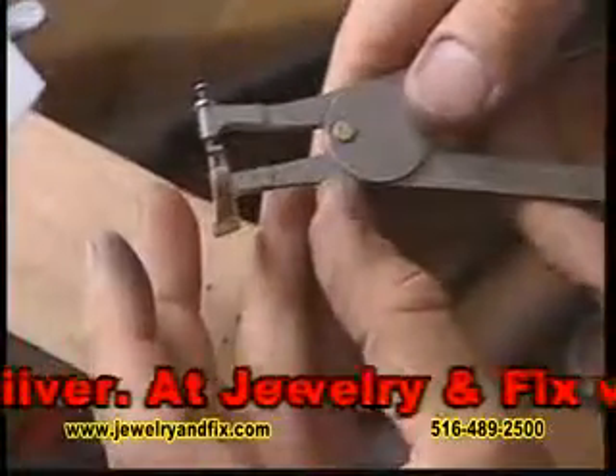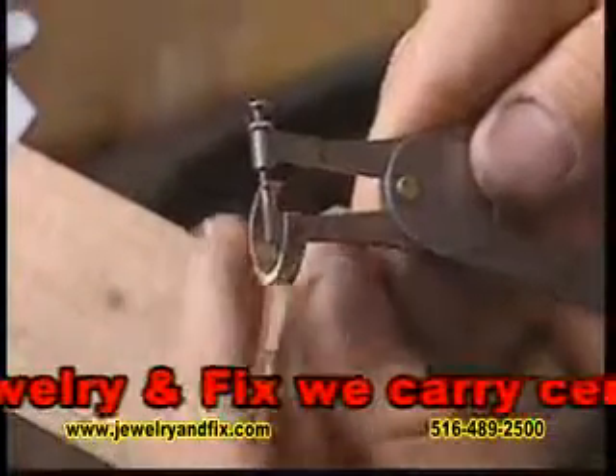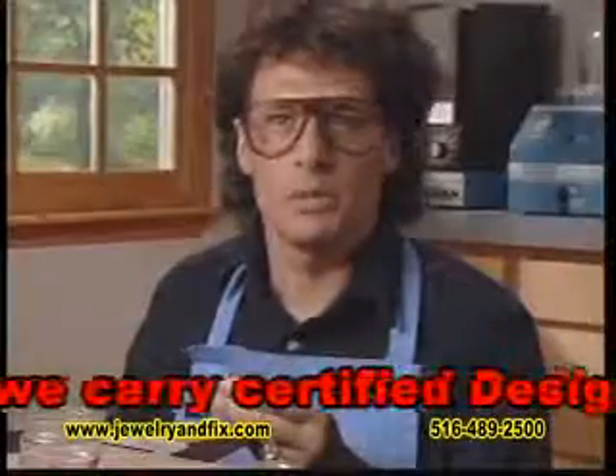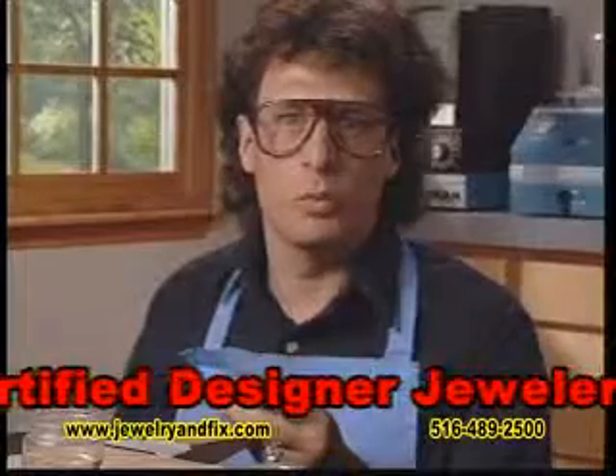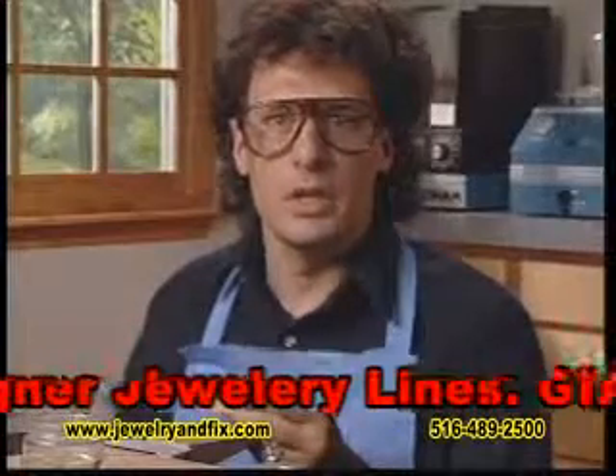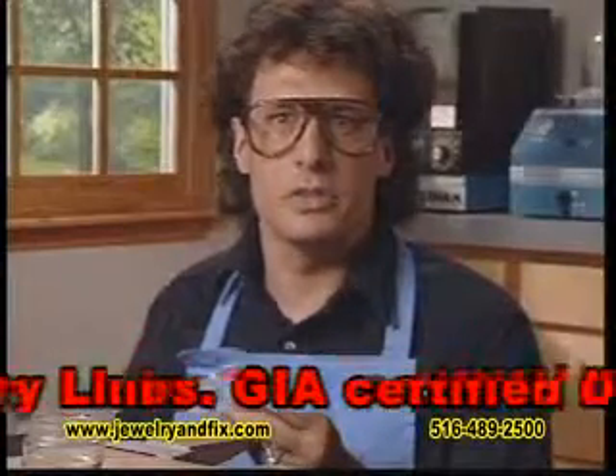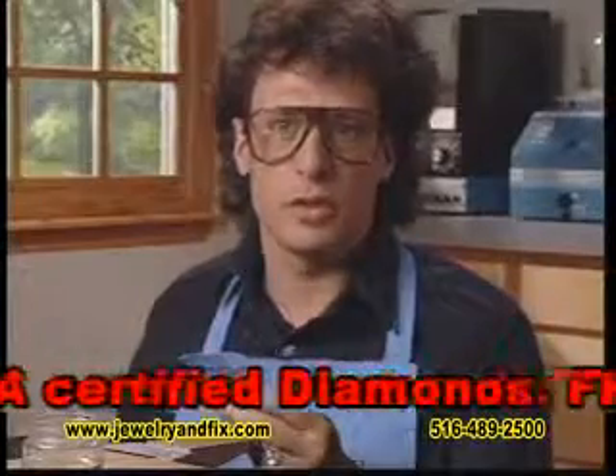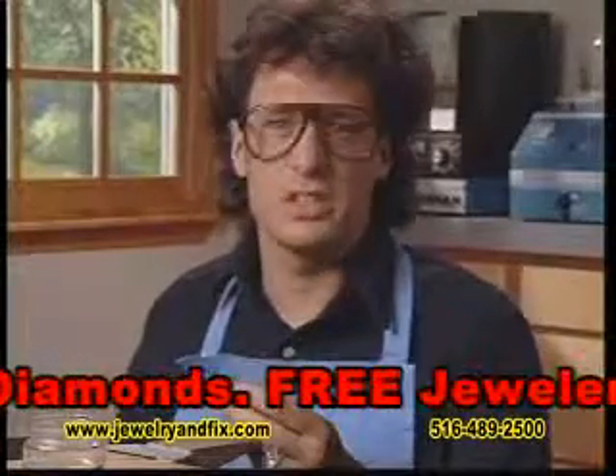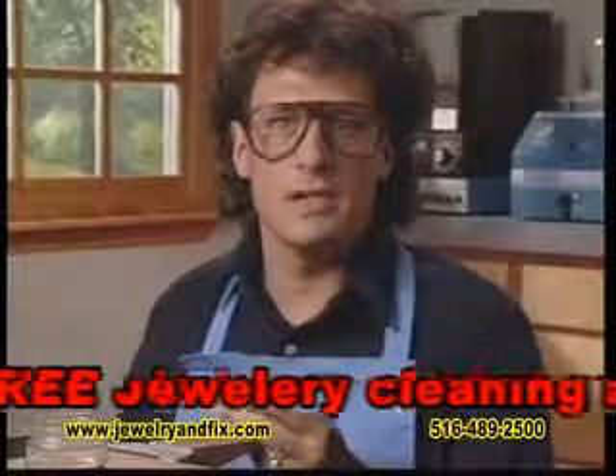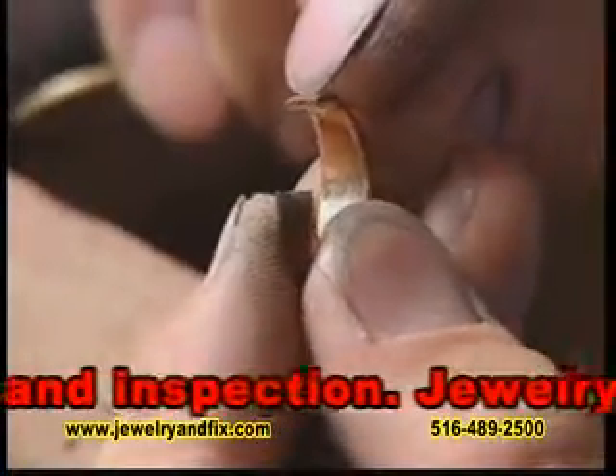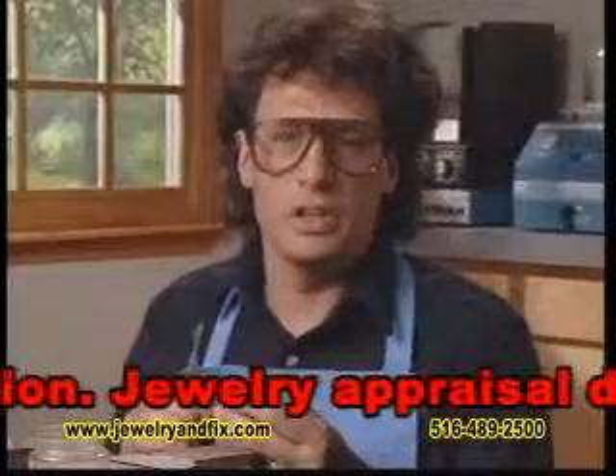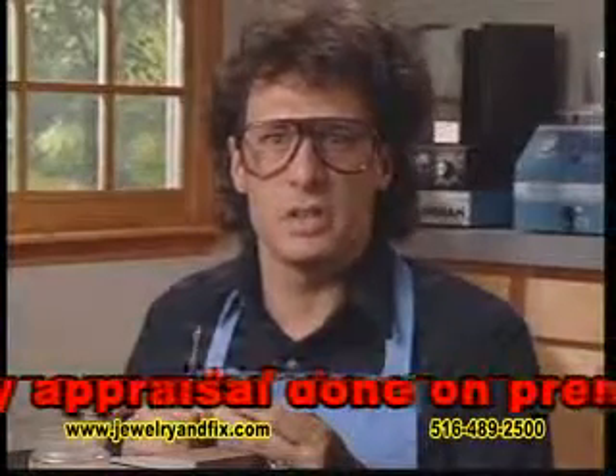I'll take a measurement on the ring, which is approximately 1 millimeter thick. I want the new piece to be approximately 1.3 to 1.5 millimeters. It's important to use a larger piece so that you can file the ring down to the correct contour. If you use a piece that's the exact same thickness as the ring, you may run into some problems and make the ring thinner. When a ring comes in for repair, the ring should leave the shop the same thickness as it came in.